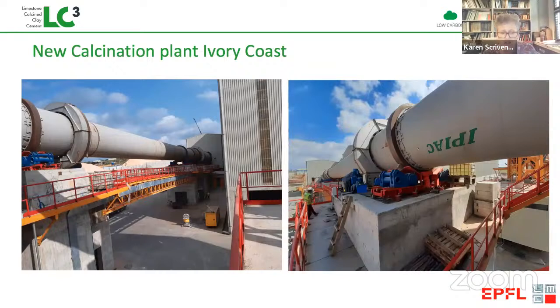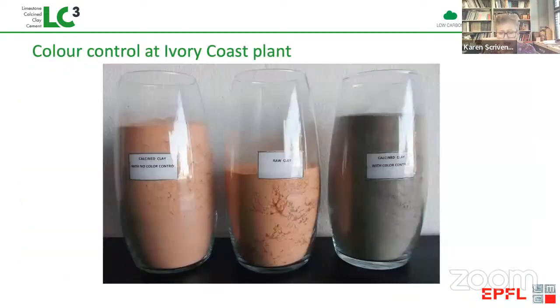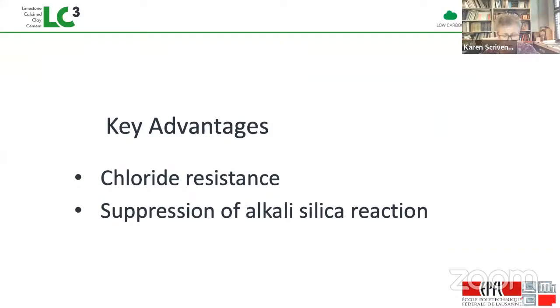What's particularly interesting about this plant in the Ivory Coast is that there it's possible to control the color of the clay with a quite simple technology coming from the brick industry. You see, this is the red clay, but if you don't want to have red cement, you can quite easily, during the calcination, transform this clay to this normal gray color we associate with cement.